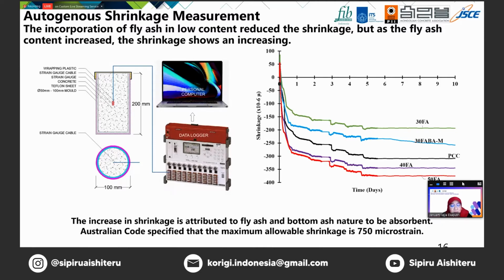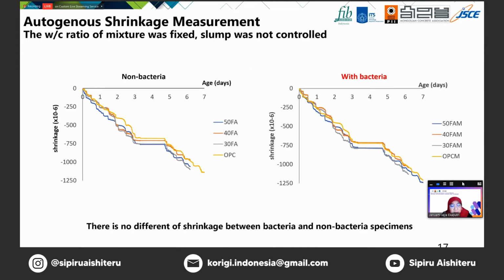This is caused by the ash content and good compatibility and good compacting of the mixture during the casting. And it is also very interesting to see that if we do not control the slump, we just keep the water to cement ratio constant in our mixtures to guarantee the moist curing, and we have to guarantee the moist curing up to 10 days.